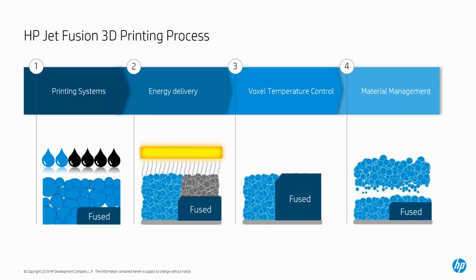As you can see right now, the system itself uses a multi-agent process in order to fuse the parts together. Essentially what we do is we disperse 2 different types of agents across a bed of powder. One is referred to as a fusing agent, which is outlined in the black droplets that you see on the left-hand side. The other one is the blue agent or translucent agent, which would be a detailing agent, which gives us nice details and cools off the part as we print.